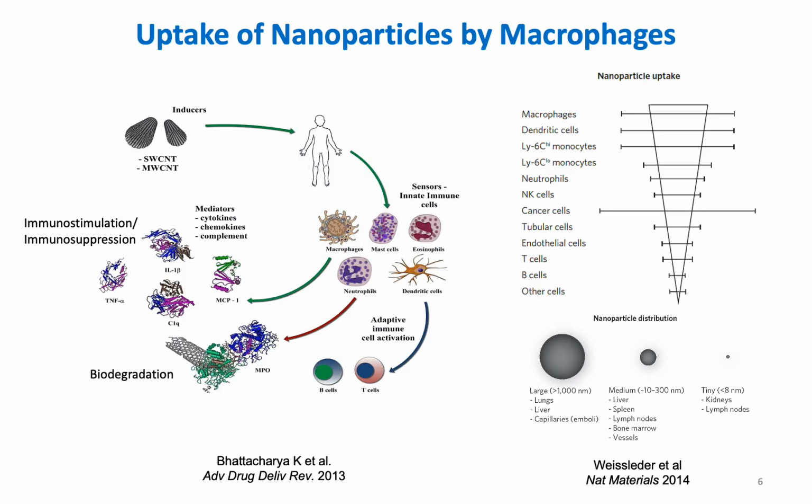For example, bigger nanoparticles end up in lung or liver, while small nanoparticles smaller than 10 nanometers are eliminated through the kidney in urine. So we aim to develop nanoparticles with a size between 10 and 200 nanometers for the treatment of cancer.